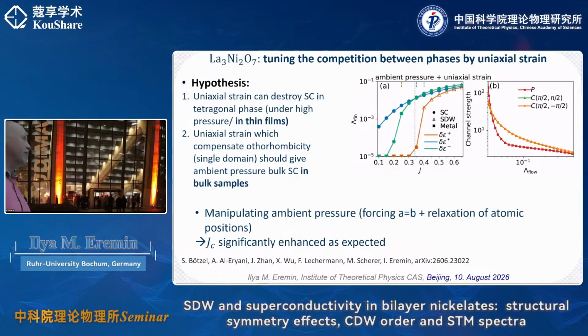And this is what we have effectively done, where we took the band structure from the orthorhombic case, applied a compensating strain, then did a relaxation, and afterwards again did the FRG calculation. And we see that the critical scale where superconductivity rises is essentially shifting. So it actually moves towards a more tetragonal situation. This is also a hypothesis which would be nice to check, because it would unambiguously establish a connection between superconductivity and magnetism. Since there is a structural transition in between, it's still a question whether the magnetic phase is really a parent phase. But by doing this experiment, you can prove whether it's a parent phase or something else.